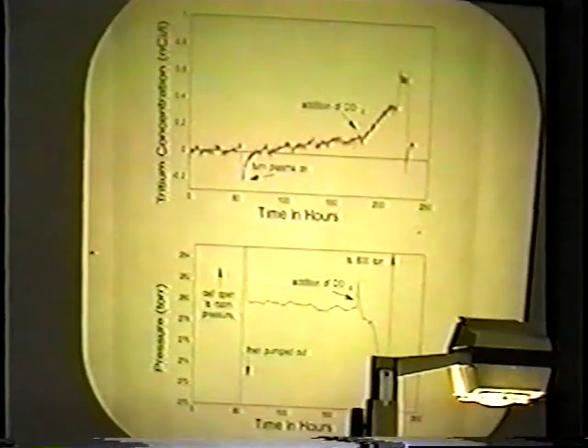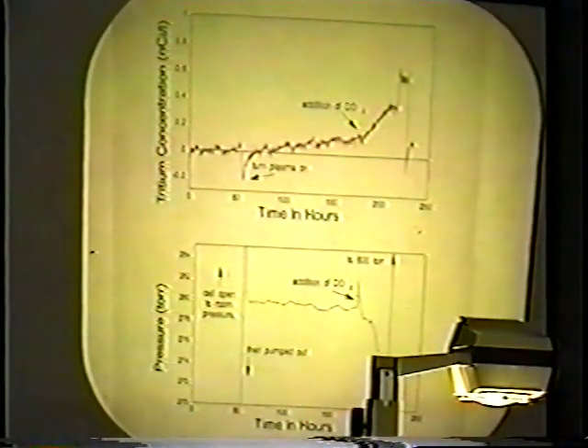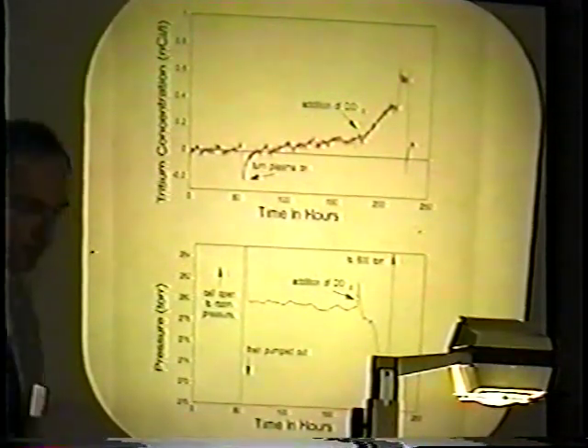But it continues to drop, and that means that what's happening is the material is hydriding. And so it actually hydrided probably prior to that, but it continues to hydride. And this is one with a large plate, so we can actually follow this. And then we pressurize that, and it gives up to this value here and make our quantitative measurement.